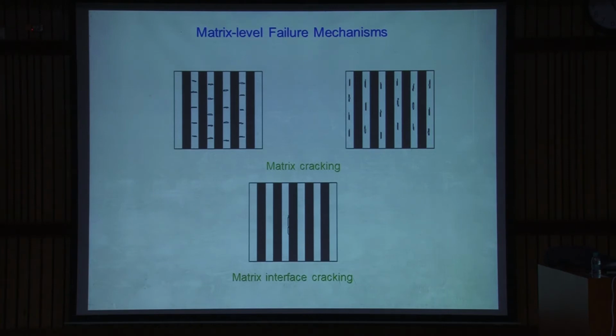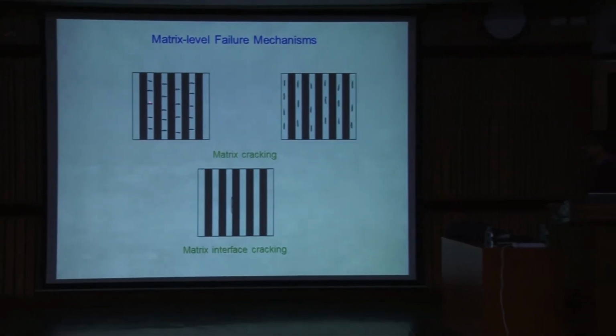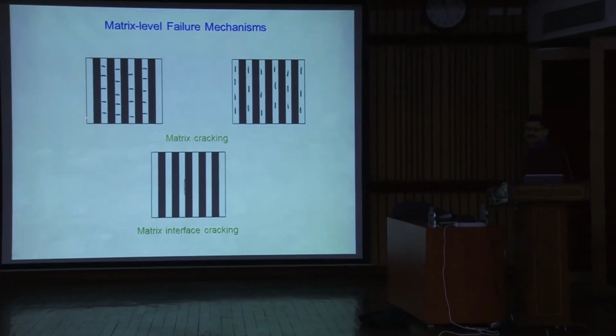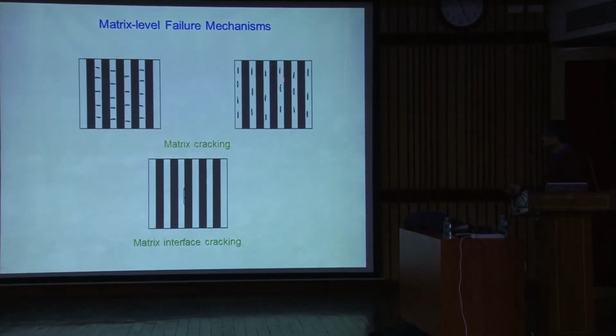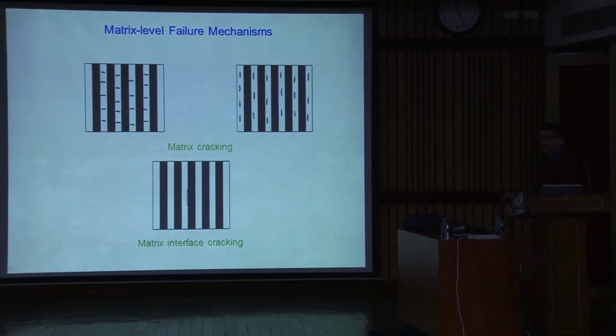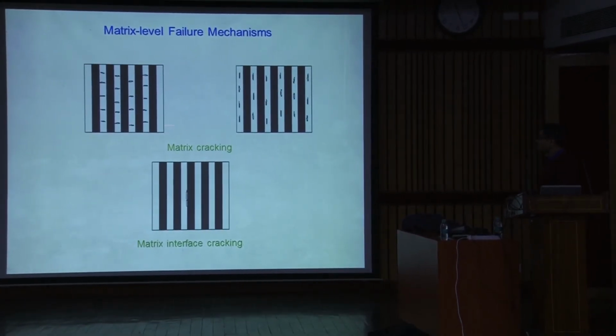Then another level of failure is that this matrix between the adjacent fibers can develop cracks. So, there are two types of cracks. In one, these cracks are developed perpendicular to the fiber length. In the other one, they are developed along the fiber length. Depending on the loading and the strength of the matrix material, either of these is possible, or both of them is also possible.